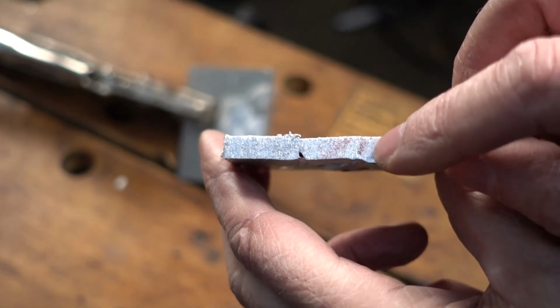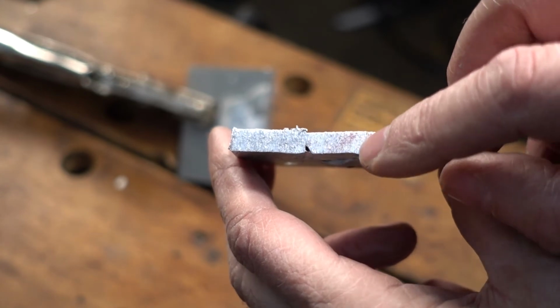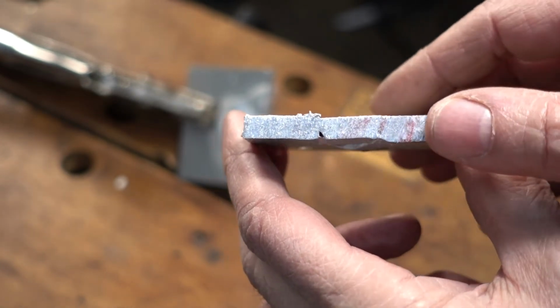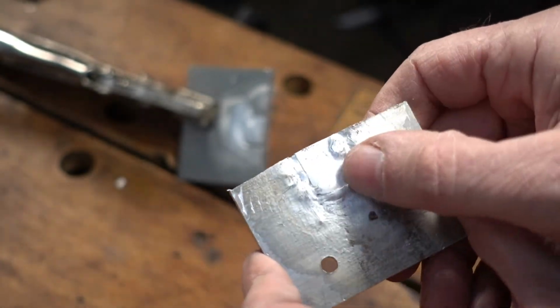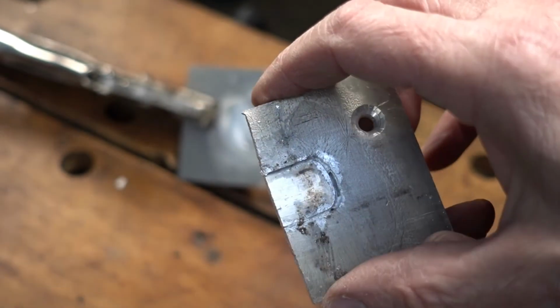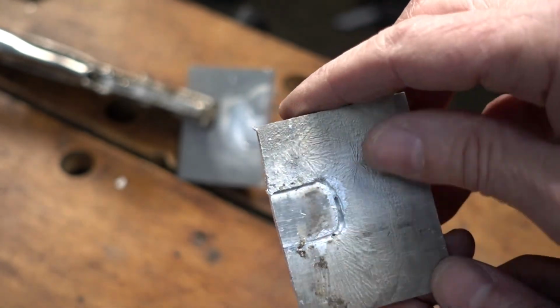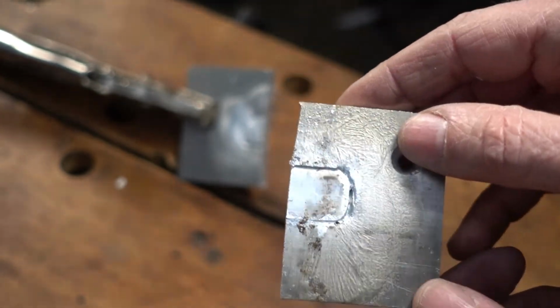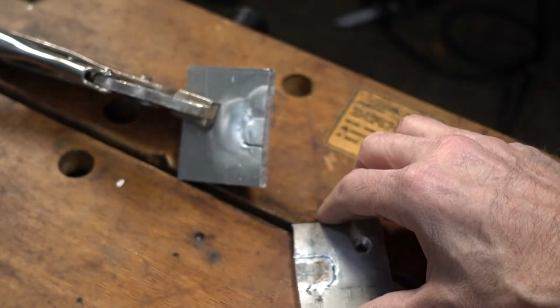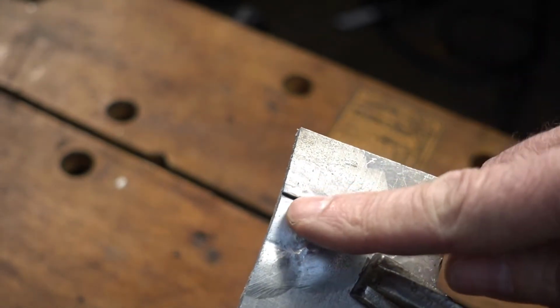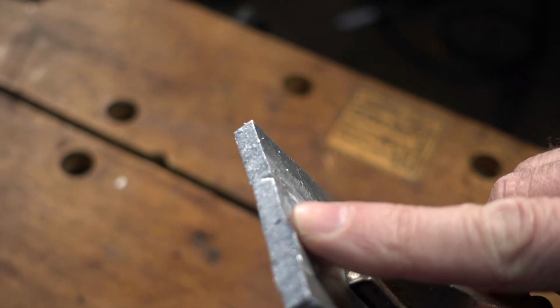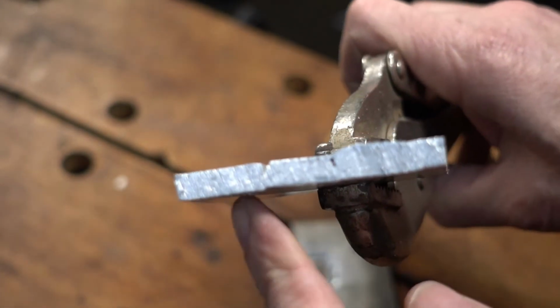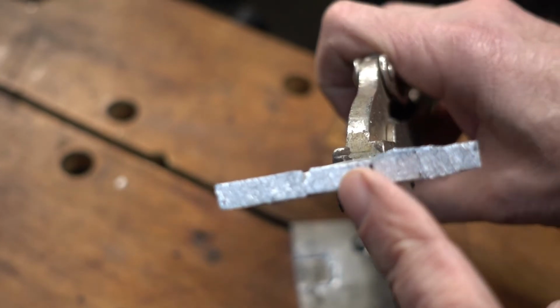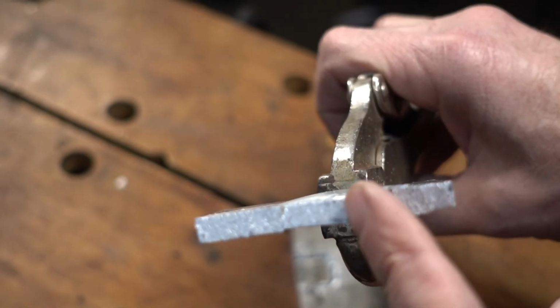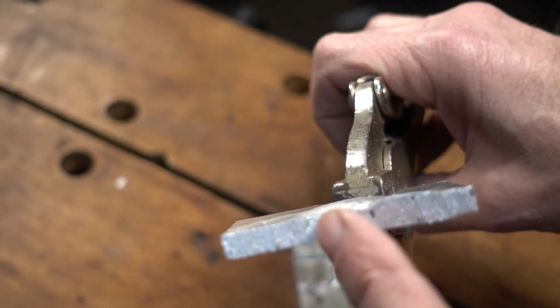And you could see penetration on this side of the aluminum. The aluminum flux did not get full penetration on that side, and you could see where it shrunk. I think one of the keys to take away is it does have an application for certain uses, and also you can't keep the heat on it all the time because you're going to lose your flux. It will drip away. And here's that piece where we didn't get full penetration. You could see on the edge it got some penetration at the bottom, but the heat drew the aluminum flux in, and it didn't really sit on top of the plug.